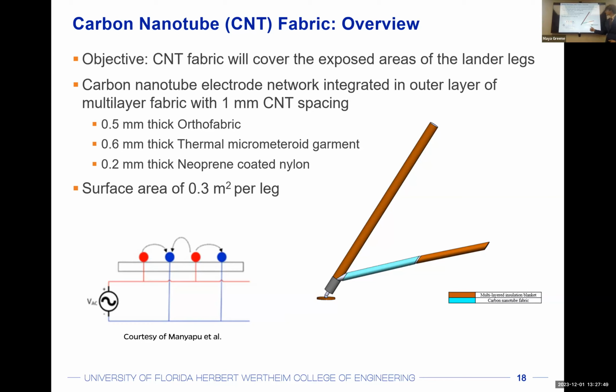This fabric works because it has a network of carbon nanotube electrodes through it. This network consists of two parallel rows, which have extending columns of carbon nanotubes out of it that do not connect. These parallel columns have 1 millimeter spacing, and when an alternating current is sent through it, it will generate an electric field around the fabric, which will push the charged dust away from the fabric.